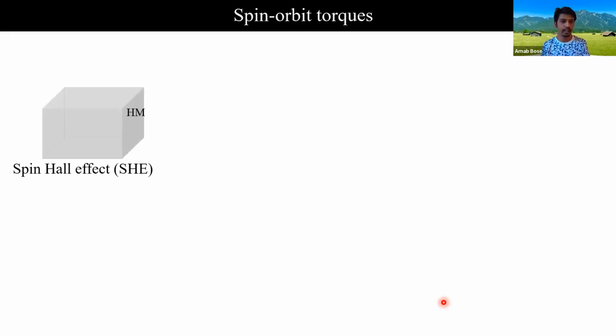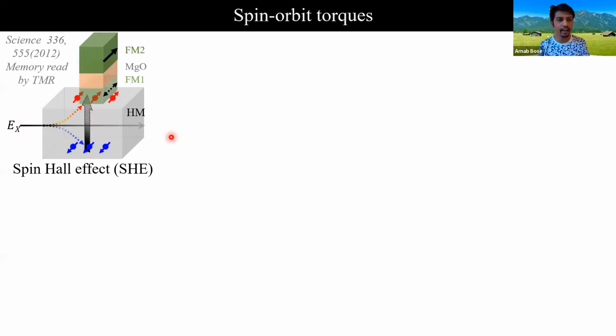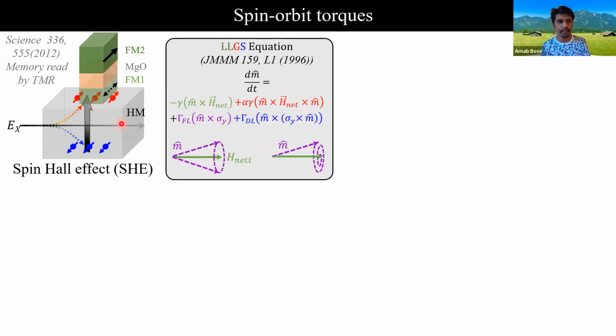So let me start with a brief discussion of spin orbit torques. For the spin orbit torques, we need a source of spin current. One of the ways to generate efficient spin current is by the spin Hall effect. For this, we need a heavy metal. When we run in-plane current in the heavy metal, or when we apply an in-plane longitudinal electric field, it creates a transverse spin current, where the spins are polarized perpendicular to the direction of both the electric current and the spin flow direction. Now, when we have an adjacent magnet, it absorbs this spin current, and it experiences damping-like and field-like torques. Now, if we have a very large spin current density, more than a critical value, then we can switch the polarity of the magnetization of the free magnet.